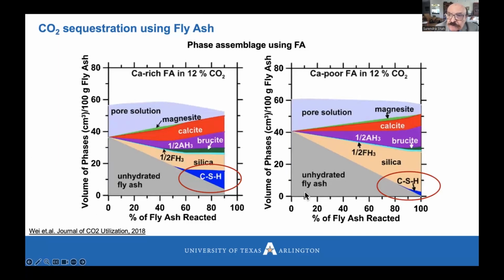So when you use class F fly ash or low calcium fly ash, then after carbonation, there is not much calcium left. So you don't have this important binding glue, calcium silicate hydrate. However, with higher calcium content fly ash, you have sufficient calcium to produce carbonation and strength-gaining CSH. So it's important to use high calcium fly ash.